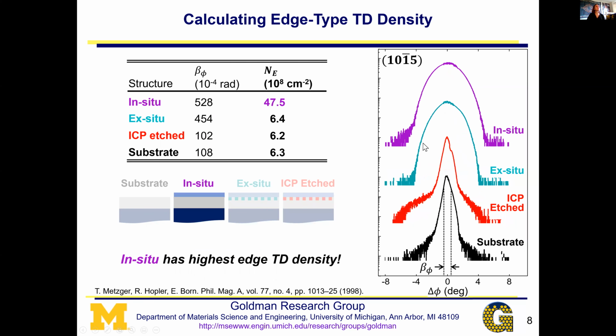On the other hand, here are the results for the edge type threading dislocation densities. You can see the peaks here look very different than the previous ones. The main takeaway here is that through a similar analysis of quantifying peak width, I can then get a figure or a number for the edge type threading dislocation density, which in this case is the highest for the in situ sample. So again, this in situ sample is the one that was grown without interruption, and it has the worst crystal quality in terms of edge type threading dislocation density.